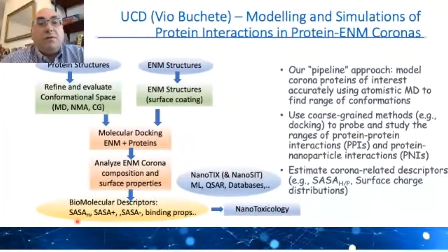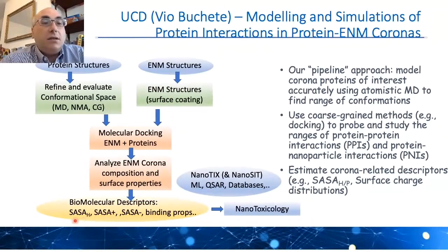So I'll use in this talk my abbreviation for this descriptor, SASA. SASA is the solvent accessible surface area, an important biophysical descriptor that tells us about how hydrophobic, in this case, or hydrophilic, or charged, positive, negative, the protein covered nanoparticles are.